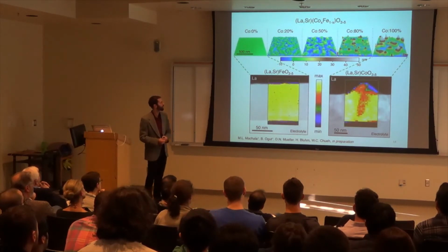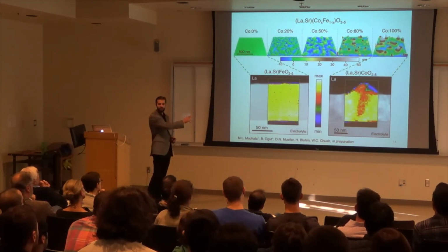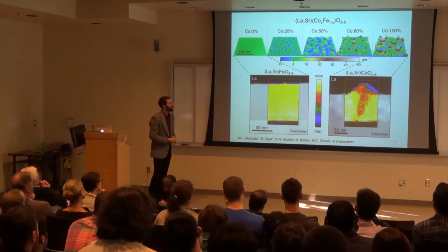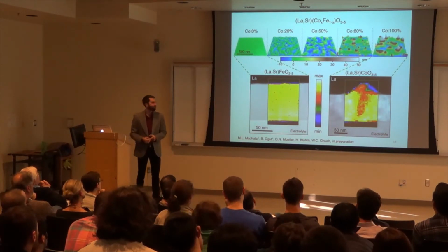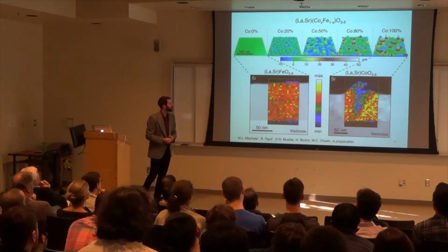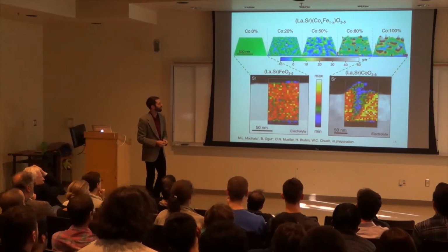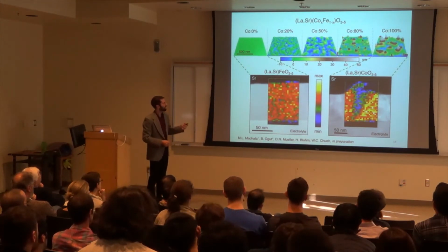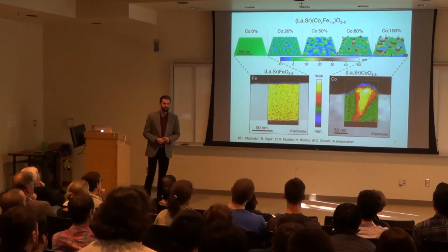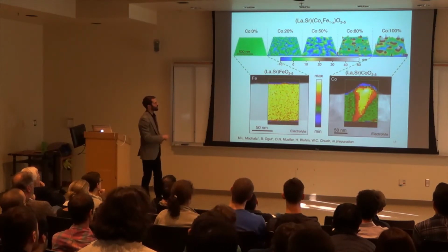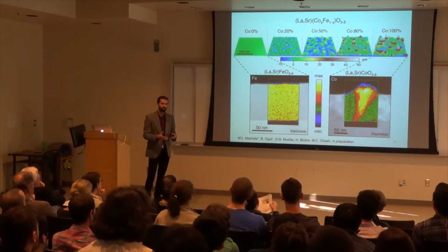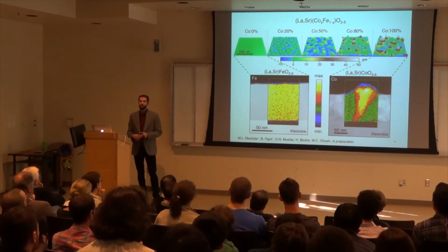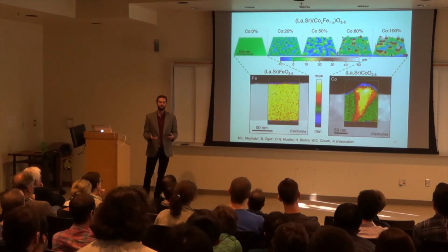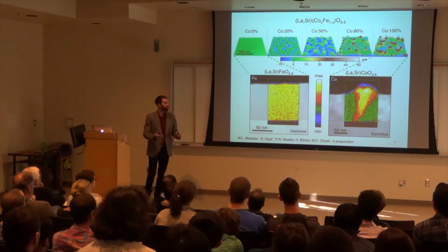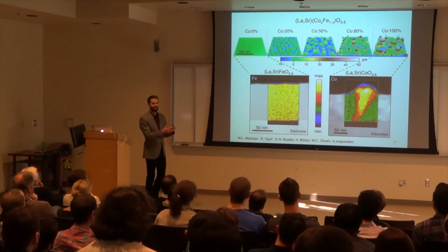So we look at lanthanum initially on both of them. We see that it's relatively uniform for the iron species. But if we look at the other side on the right, we see that there's a deficient area within this large bump for lanthanum. If we compare that to strontium, we see a similar thing for the iron and the deficiency of the strontium on the right side. And now, what's illuminating is when we look at the transition metals, the iron and cobalt. The cobalt side shows us that there is an enrichment of cobalt over in these large bumps. And now cobalt, when you put it into the material, likes to create a lot of oxygen vacancies. And the oxygen vacancies can order. And so essentially what we're seeing here is a demixing of the perovskite into the cobalt-rich phase and the perovskite itself.